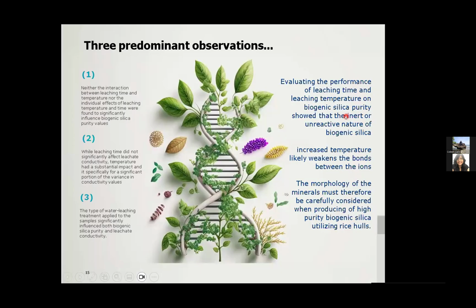So for a summary and conclusion, there are three predominant observations. First, neither the interaction between leaching time and temperature nor the individual effects of leaching temperature and time were found to significantly influence biogenic silica values. Number two, while leaching time did not significantly affect leachate conductivity, temperature had a substantial impact, specifically for the portion of the variance in the conductivity values.